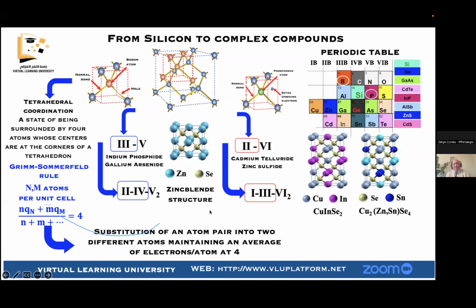The two ways are different. The way here, going from silicon to 3,5 compound, needs a very expensive system. However, for going from silicon to 2,6 compound, you can do it with electrodeposition, a very simple method, and this is very important. And of course, you can control the stoichiometry, the band gap, and the doping. For silicon, you can control the doping very well because you have to take boron or phosphorus. But for compounds like 2,6 compound or 1,3,6 compound, it's just a native defect giving you the N-type or P-type.